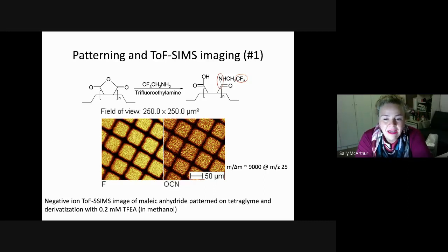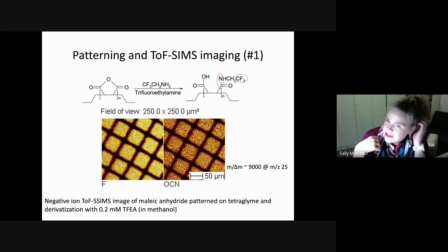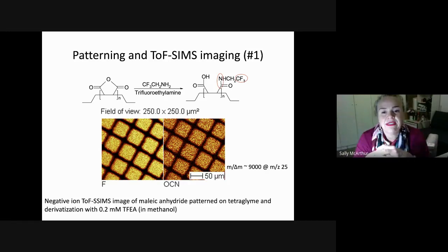And this is a maleic anhydride now patterned onto a tetraglyme surface. So this is an ethylene oxide-based plasma polymer. And if you actually do, again, that derivatization experiment to look for where the fluorine goes when you functionalize the surface, you can see that we can successfully, quite cleanly pattern the anhydride onto the surface, and it's still reactive afterwards, which I found fascinating, because this has had all of those processes done to it. It's had UV light exposure to do the development of the resist. We can take the resist off, and the